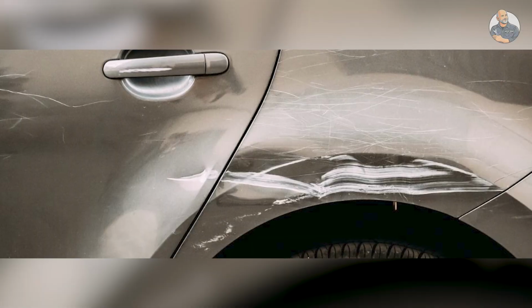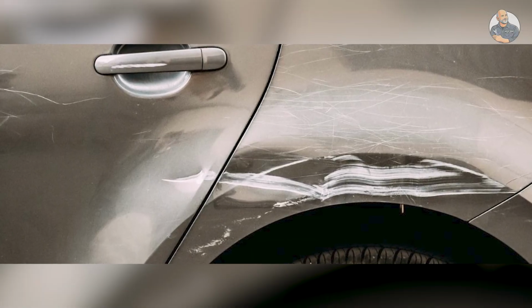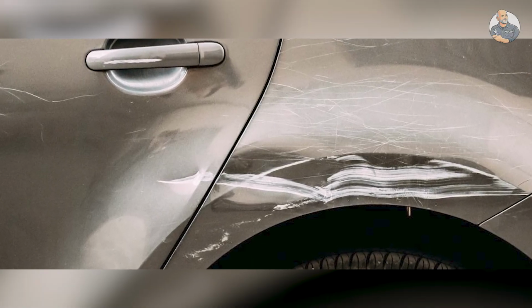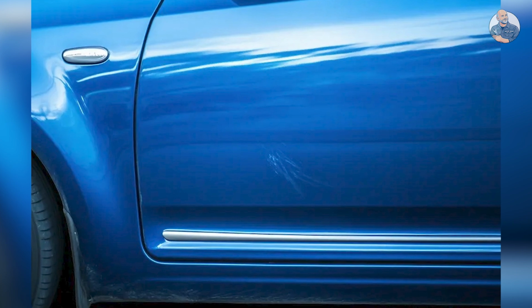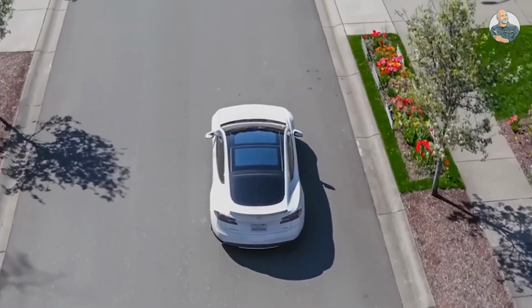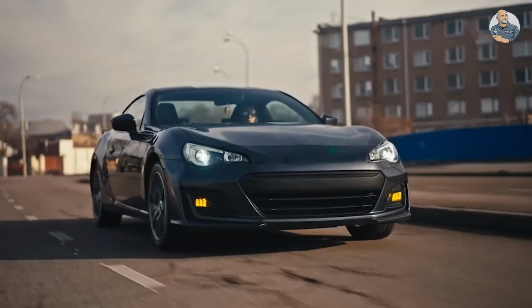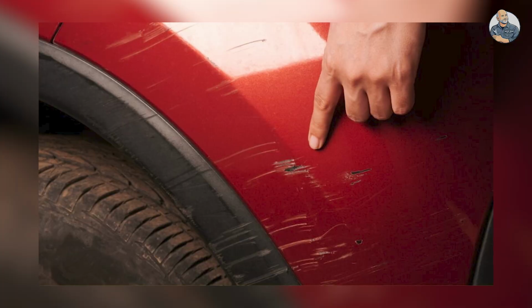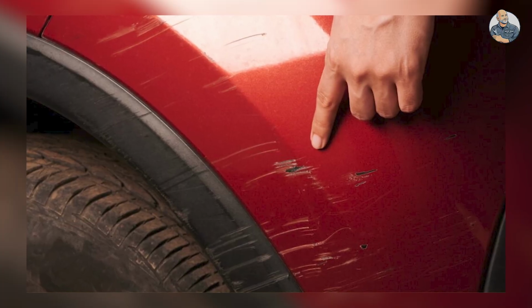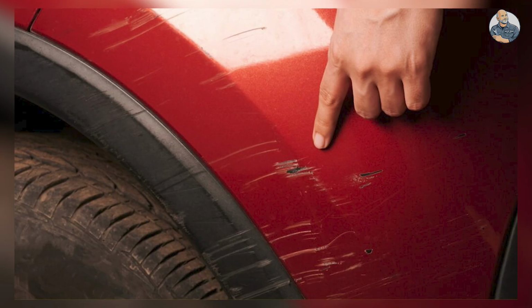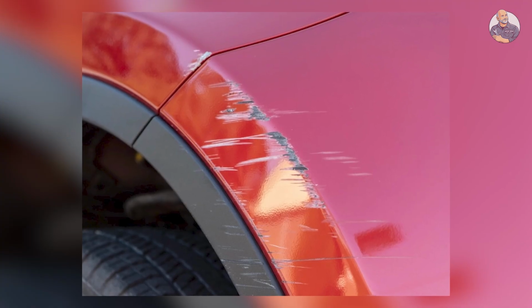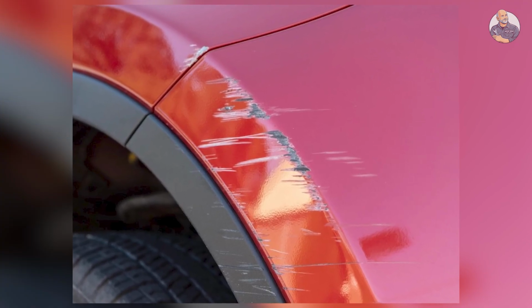The second case, I want to mention large areas of flaking paint. Carbon only acts as a filler for scratch grooves. When a large paint section is missing, the surface bonding structure is completely destroyed. Carbon powder cannot restore uniform color or aesthetic consistency. Applying it in this scenario would only create a dark patch on a lighter paint background. On light-colored cars like white, silver or gold, carbon powder will stand out if not covered with a color-matched touch-up paint. In such cases, the painting step is mandatory to unify the surface.